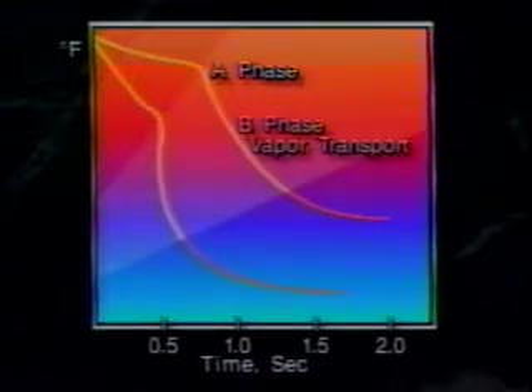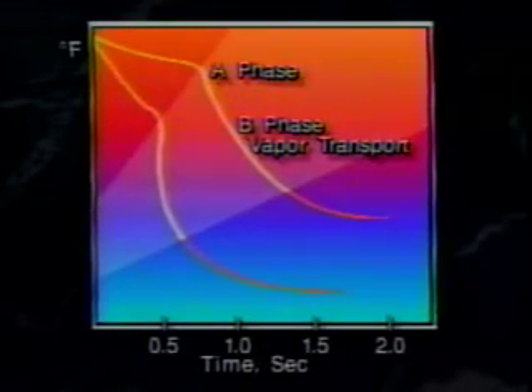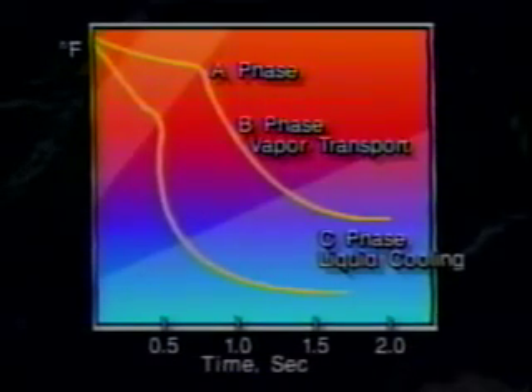The B phase of the quench is the vapor transport phase. During this second stage of cooling, the vapor film has completely collapsed and there is rapid heat transfer along with violent boiling as fresh, cool liquid continually contacts the surface. The C phase of quenching is the liquid cooling stage. The surface temperature of the part has been reduced to near boiling. No more boiling of the quench fluid occurs. The rate of heat extraction is again reduced to a level much slower than that measured in the B stage. This phase of quenching is sometimes called the tail-out. Agitation of a liquid quenchant helps break the vapor blanket and promote a faster heat transfer.